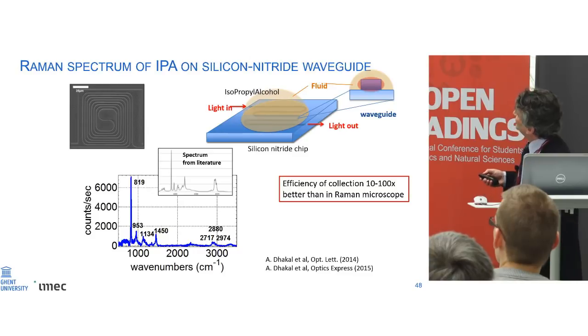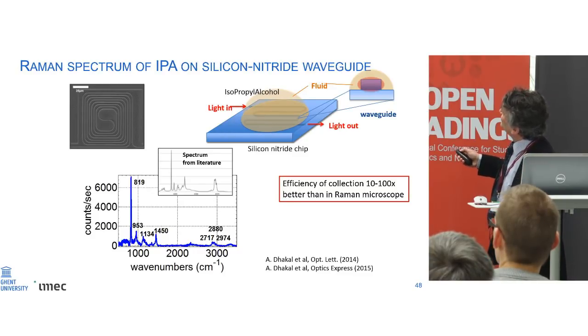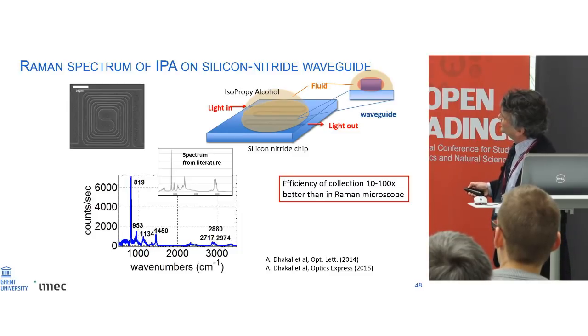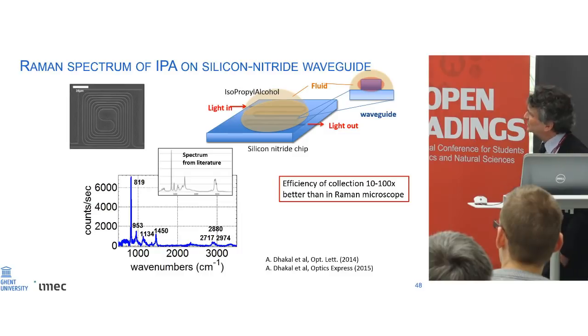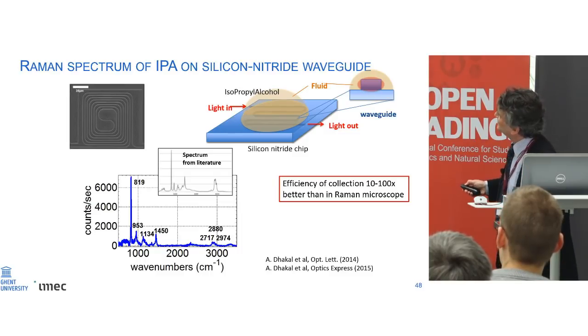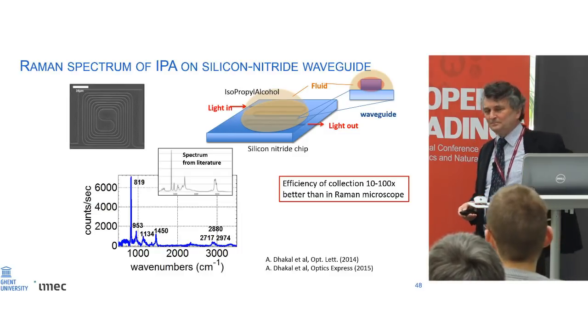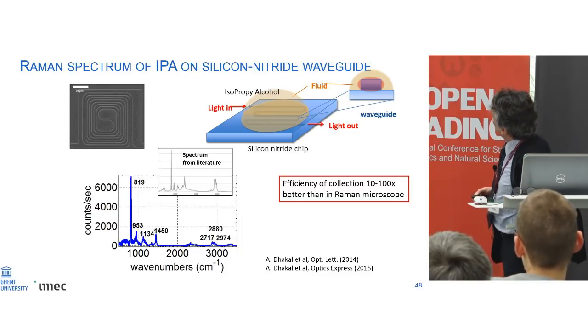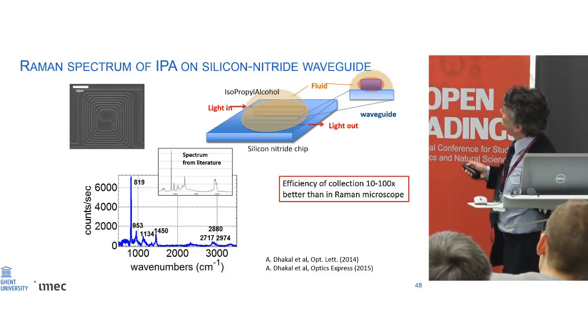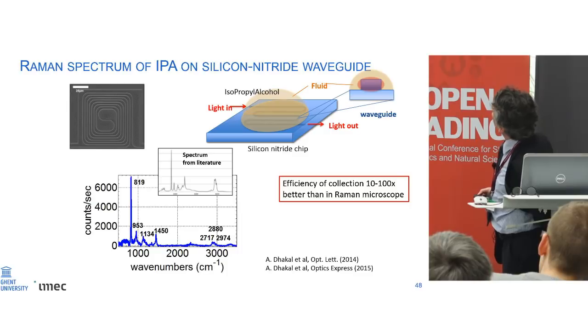And yes, this works. If you take just a chip, you put, for example, a drop of, in this case, alcohol on it, and you observe the spectrum of what comes out of the waveguide, this is what you see, and you see a number of vibrational peaks, and then you go to a database to compare it with, and you find out which molecule it was. Of course, we knew that we put IPA on the chip in this case.